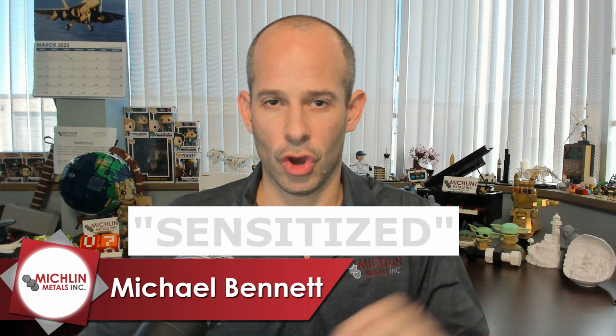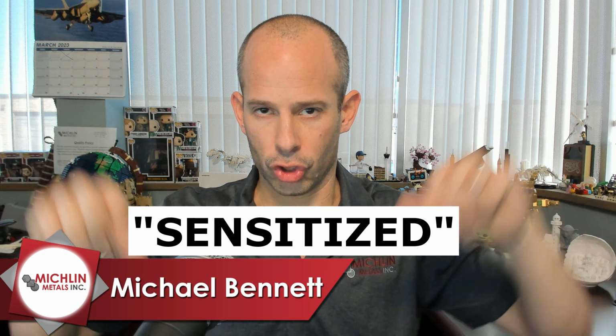But if we expose the material to an elevated temperature where diffusion can occur, carbon atoms can migrate toward grain boundaries where they can combine with chromium to form carbides. Unfortunately, this depletes the chromium level adjacent to the grain boundaries, creating a path for corrosion to occur. It has been sensitized.